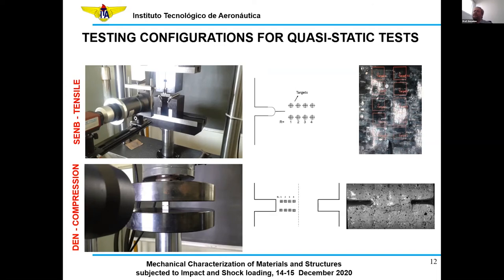On the left-hand side here, you have two pictures showing the SENB and the DEN configurations, where we have specimens loaded under the quasi-static regime. If you look carefully here at the crack tip, what we have done is we white painted the specimen, as all the specimens used in the DIC measurements require. We sprayed some black speckles on it, and we defined some targets required by the video gauge measurements. We use the video gauge here to measure the strain field at the crack tip.